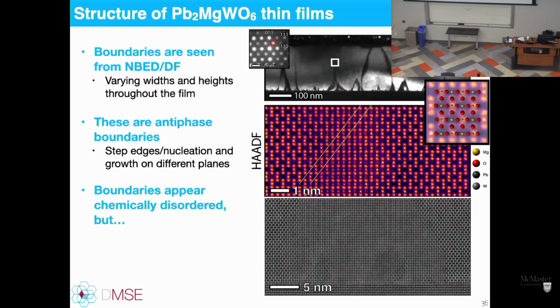They're offset. So when I bring these two offset parts of the crystal together, I would try and align tungsten and tungsten, right, from the octahedron. They'd be right next to each other. As a consequence of that, they're going to be very high charge state. And so you might think it's going to chemically disorder to try and decrease that charge. But the important thing to know, they appear chemically disordered, but are they?